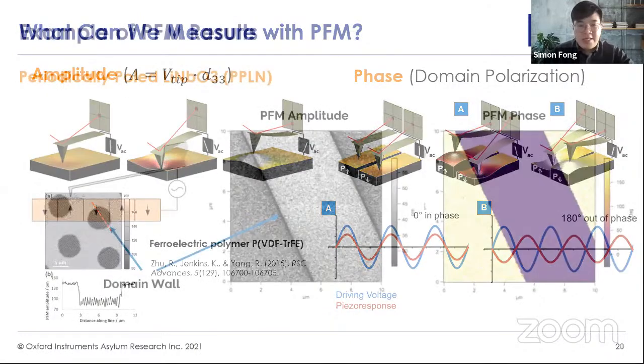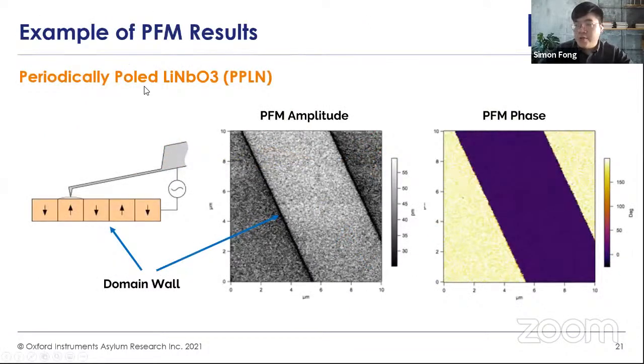So let's look at an example. This is a periodically poled lithium niobate sample. The image shows a cross section which has down domains and up domains, and also the domain walls, or domain boundaries, that you can see. Let's switch to the right side, the PFM phase. You can clearly see that there are two shades of color here, purple and white-yellow. This shows there are two different phases, and this represents two domains, one representing the up domain and the other the down domain. That is the use of the PFM phase, as I explained earlier.